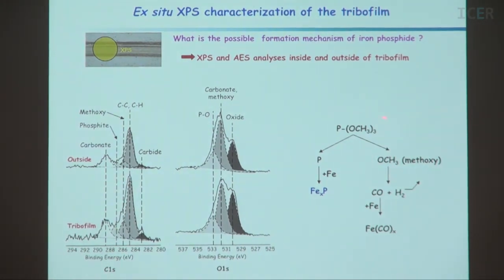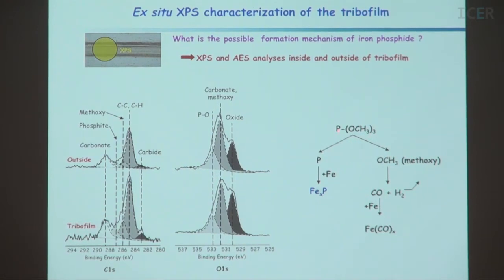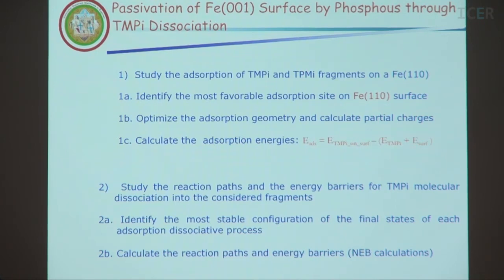Now the mechanisms are quite complicated, because starting from these molecules, we get to these surface products, iron phosphide. So this is a chemical pathway we can imagine to come from this molecule to this compound, phosphide, and maybe other species from methoxy. So this is really chemistry. And of course, it is difficult to analyze by XPS. For example, here with the carbon peak, we can find some carbonate peak here. And in the oxygen peak, we can detect peaks. Well, it is difficult to identify exactly. So here we use computer simulation for this case.